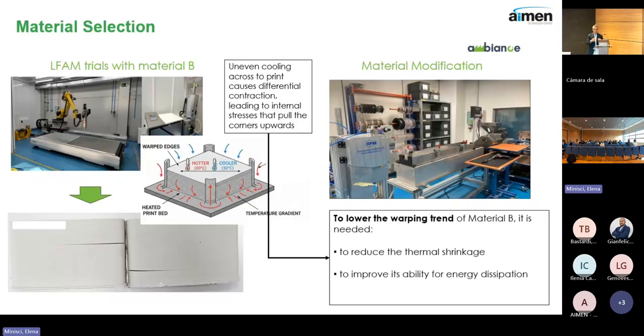By adding fillers, we are able to lower the contraction that the material is suffering. But there is another factor playing in the warping, and it's the ability of the material to relax stresses, and it's related to the viscoelastic nature of the material. And this is not something that we can easily change by adding fillers. We need to modify the chemical composition of the material.